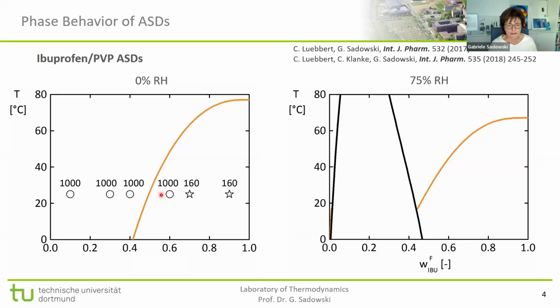This sample did not crystallize, at least not within 3 years, which is, so to say, the time of a PhD thesis. So this sample did not crystallize, but of course, this is also the one compared to the other two which is closest to the solubility line. So the driving force for crystallization is lowest, and we expect the sample to crystallize eventually. This is at dry conditions.